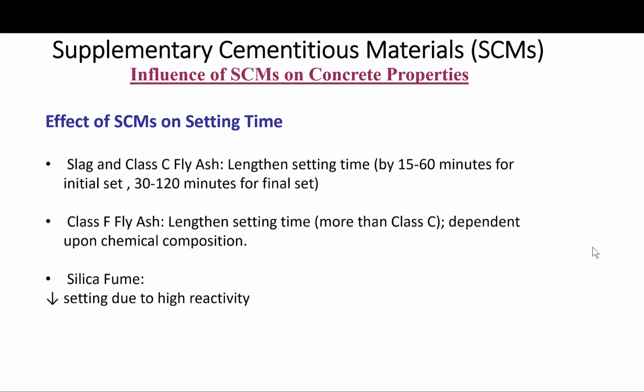For setting time, generally slag and fly ash lengthen the setting time by about 15 to 60 minutes for the initial set, and somewhere between 30 to 120 minutes for final set. Class F fly ash lengthens setting time even more than Class C, dependent upon the chemical composition, since Class C contains lime. Silica fume reduces setting time due to its high reactivity.